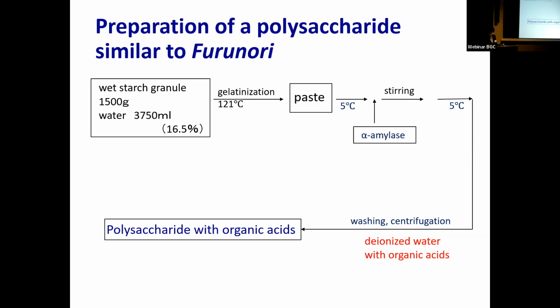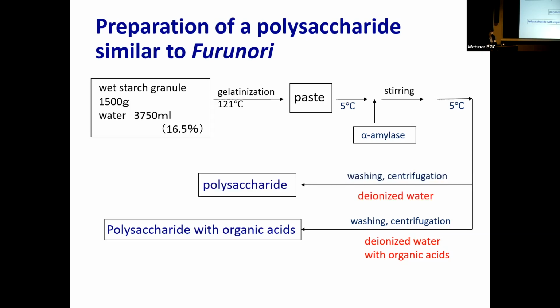aging process. These experiments with furunori also resulted in new discoveries concerning its adhesiveness. We prepared samples washed with water that contained and did not contain organic acids. We did so in order to compare their adhesive force. If they were even, we would be able to prepare a new type of furunori that was less acidic, because the high acidity of furunori otherwise could be a potential problem for the long-term preservation of an artwork. What we discovered